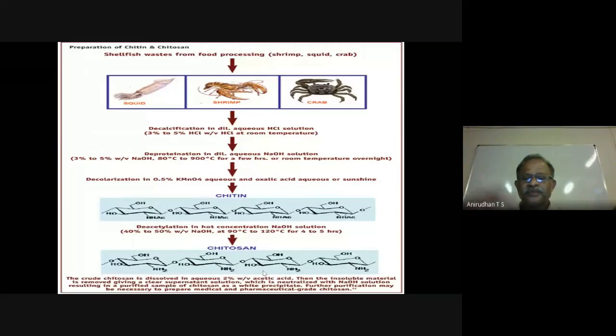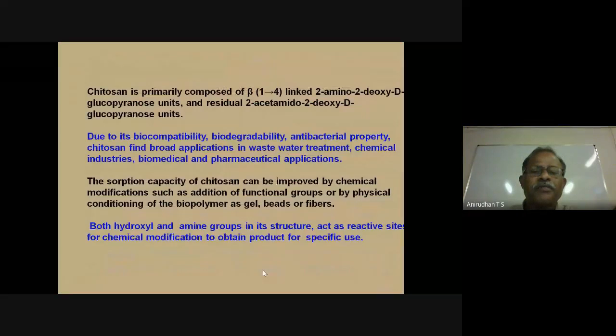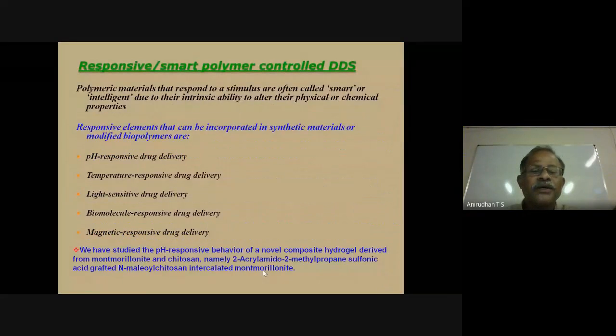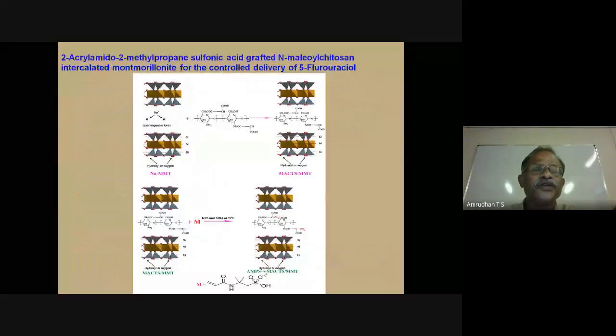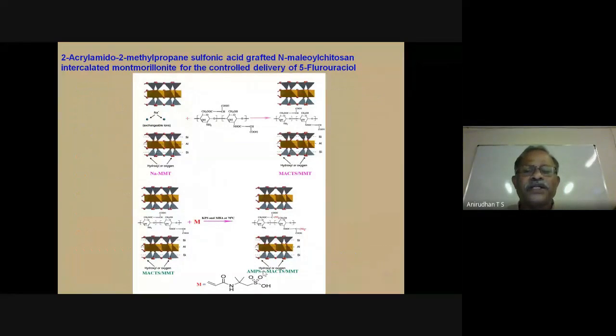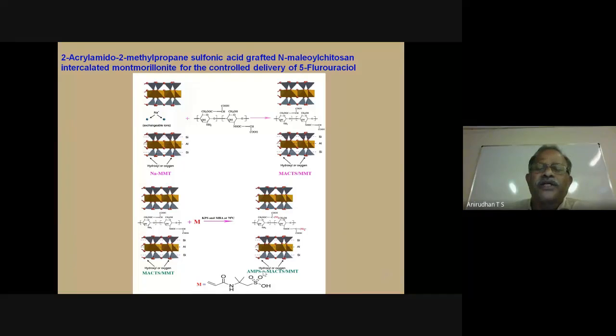And of course, now I want to prepare a large number of materials from these chitins. One of the most important materials, I have published in a paper in a high impact factor journal, maybe 9 point something impact factor nowadays, RSC Advances, RSC publications. The material is 2-acrylamido-2-methylpropane sulfonic acid grafted N-maleyl chitosan intercalated montmorillonite for controlled delivery of 5-fluorouracil. This material is very simple.